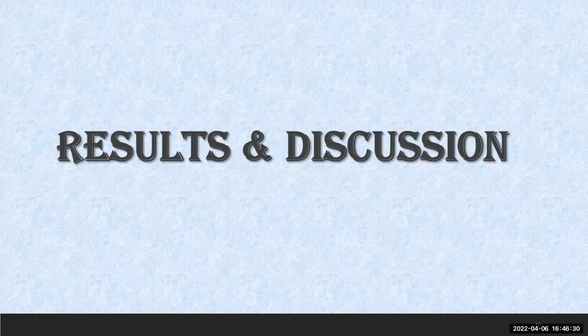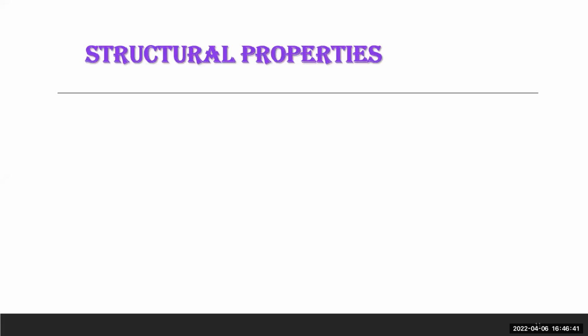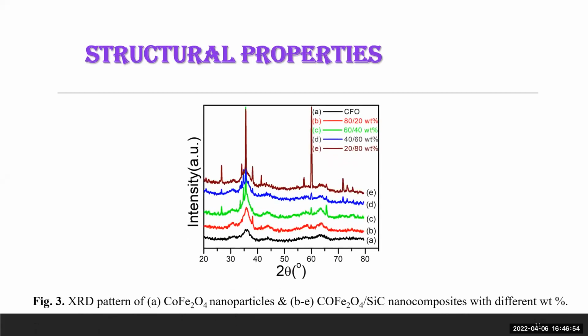Then we will move towards the second objective, that is to characterize the structural, elemental, morphological, and dielectric properties of the prepared sample. So first, the structural properties and phase identification were analyzed using an X-ray diffractometer, that is XRD, and crystalline size and phase formation of different samples were studied at room temperature. This is the XRD pattern of the cobalt ferrite nanoparticle and the cobalt ferrite silicon carbide nanocomposite with different weight percent.